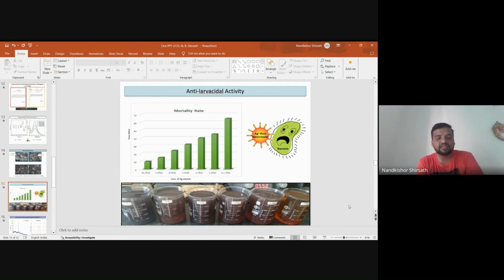As we are using silver particles, which are somewhat costly as compared to the others, we are trying to reduce the quantity of the silver nanoparticles. That's why we have prepared different ppm solutions, and we are putting 10 larvae in each beaker, and we see that the mortality rate increases as per the graph.